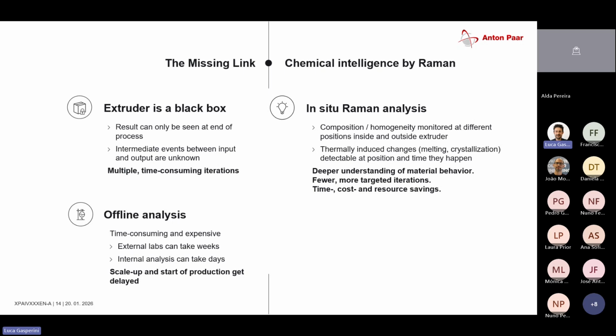Yeah, and also a difficulty should be how to clean it from batch to batch. For example, here in the extruder, you also have this problem. And when you change the recipe, you have to clean it. I mean, this is not a problem. It's a screw, so you just screw out the immersion probe, and then you just clean it. So cleaning is not such a big topic when it comes to the immersion probe. It's not fully immersed, it's just a tiny bit.